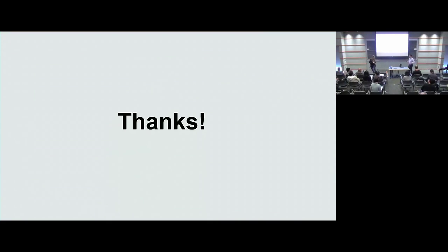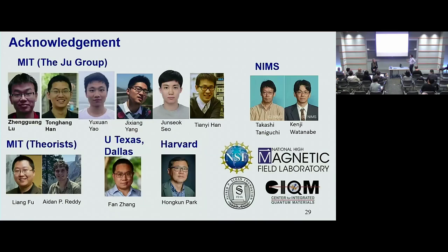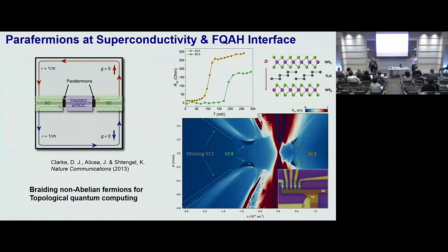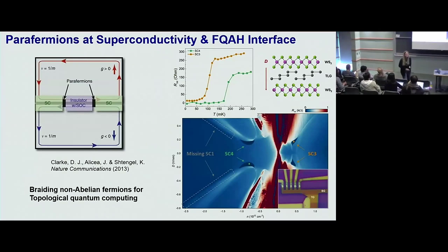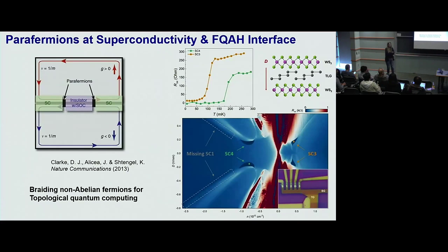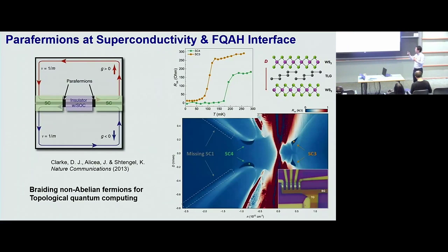Yes. Can you say a little more about this superconducting tri-layer graphene? That new result? Oh, that's new. I mean, Andrea talked about it at the March meeting. Oh, I see. I don't think he showed SC3 there, but I think he has it now. These two states are really induced by the spin-orbit coupling from the TMD layer. At the same time, we also observed that there used to be an SC1, a very long stripe here at a temperature of something like 100 millikelvin. In our device, when the SOC is strong enough, this thing got killed. So it's a mixed role, what SOC is doing to graphene superconductivity.